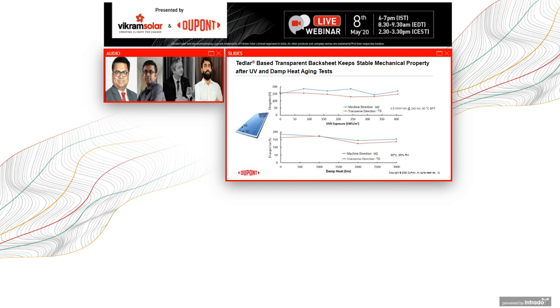Because these are polymeric materials, they can stretch, and if they become brittle, they can crack. However, if the elongation is retained, we are confident that this will hold up in the field. What we are seeing here on the top plot is elongation after UV exposure for, again, 400 kilowatt hours, which actually corresponds to 30 years of field exposure from the backside.